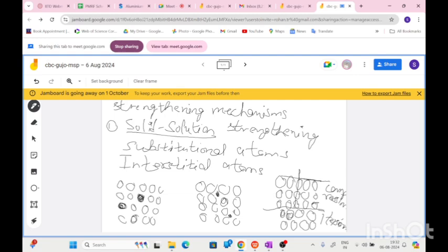To lower the stress field of the dislocation, the substitutional atom prefers to go in the tension region, or if it goes in the upper part, it imposes an elastic interaction, means the elastic modulus will be different, so there will be different types of interaction. First is the elastic modulus interaction. Elastic modulus interaction comes in when the atomic size difference is greater than 15%.